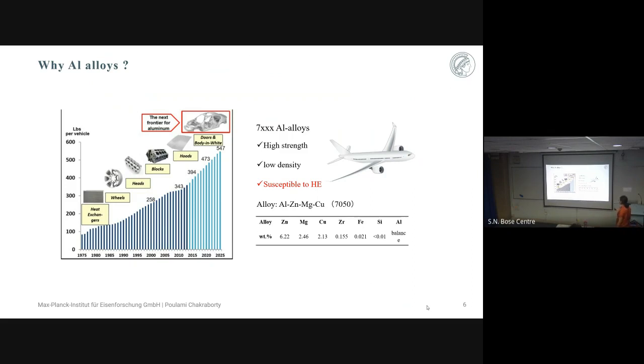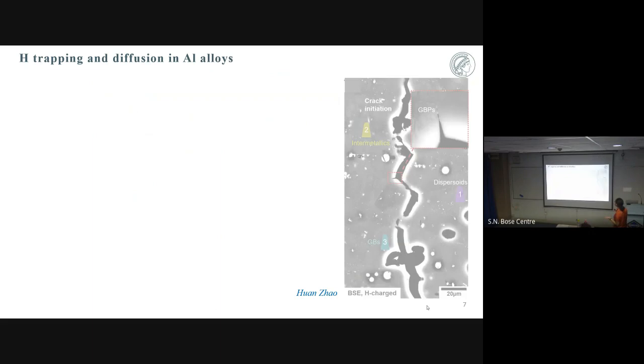As you can see here, from the weight percentage, the major constituent elements are zinc, magnesium, and copper, which is important to note here, because they will be playing an important role in the interactions in our hydrogen study. As I have discussed before, hydrogen diffusion is very difficult to study, and therefore hydrogen diffusion and trapping in aluminium alloys is what we want to discuss.